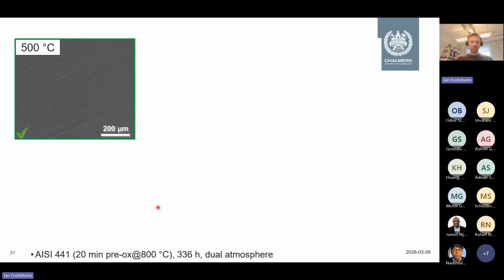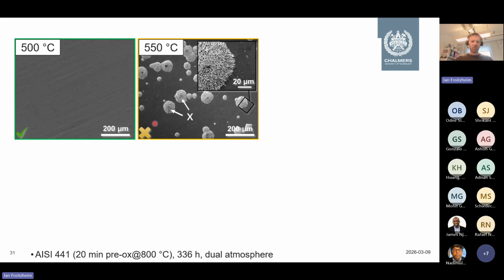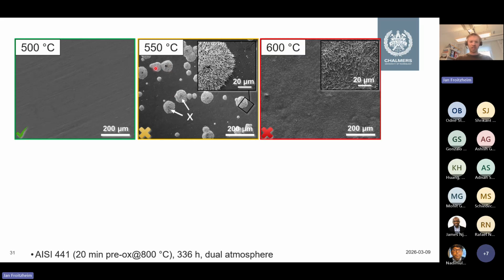At 500 degrees C, with pre-oxidized samples after 2 weeks in dual atmosphere, you see the oxide scale is very thin and protective, everything is fine. If you increase the temperature, things get worse, and you get these oxide islands of thick oxide. 600 degrees C is uniform, but it's uniformly thick, and that's basically the cross-sections you have seen before. So then it's a disaster.